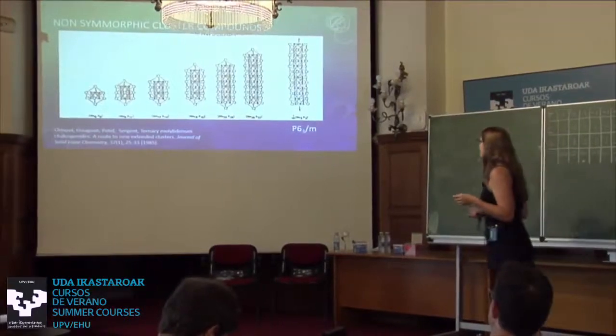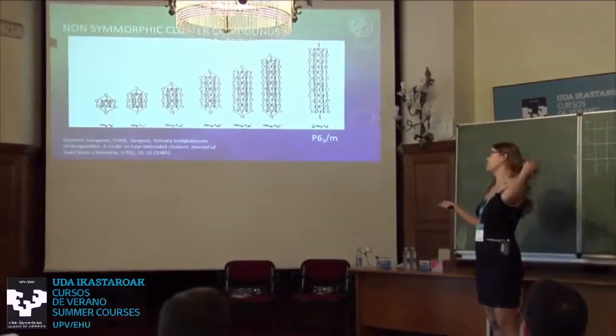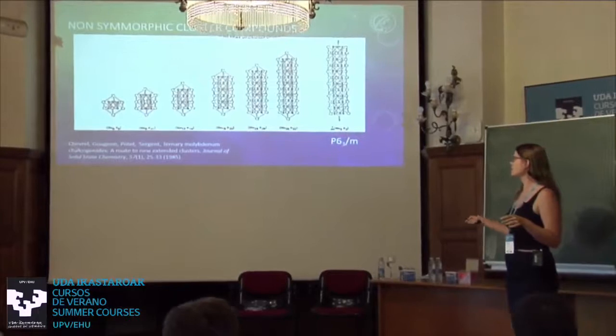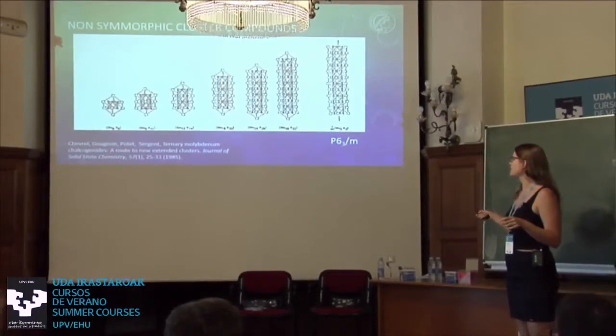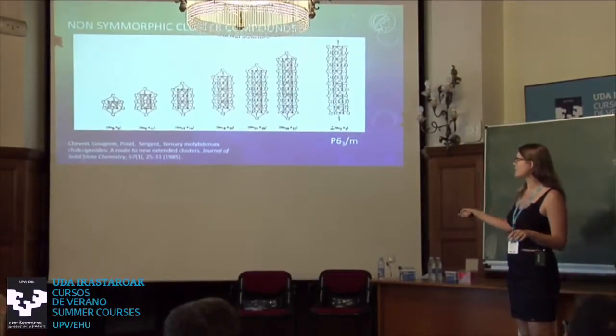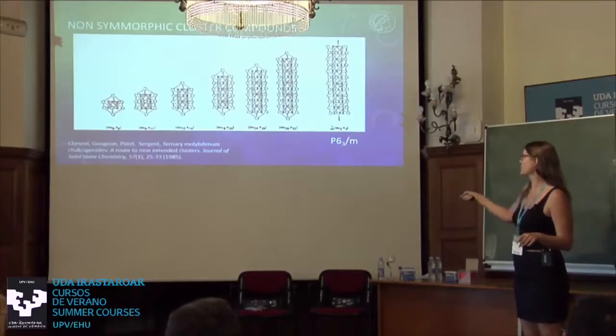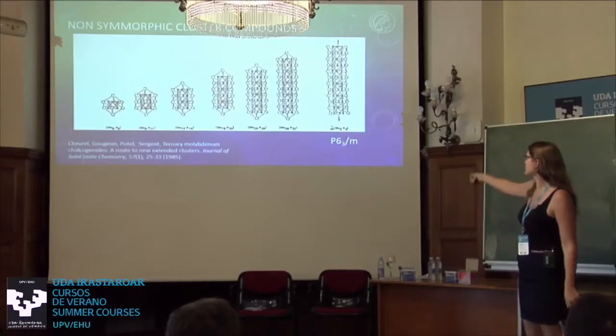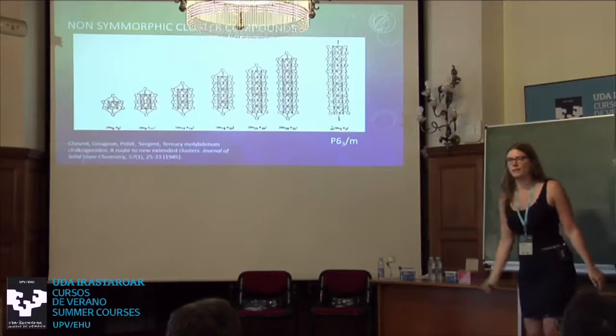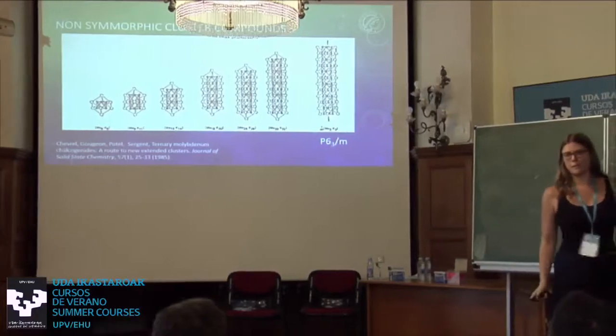But if you look at the original paper of Chevrel, where he reported these Chevrel phases, he reports lots of different sizes of the cluster. So this was the one I just showed you, but they can extend along one direction. And you can also make an infinite cluster here. And then here you have a screw axis, and it actually crystallizes in a non-symmorphic space group with a screw.